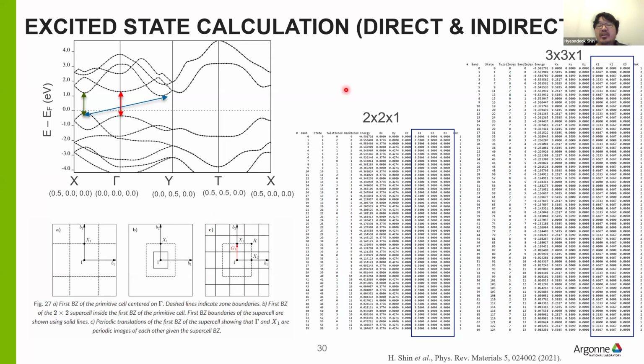So now we can make a strategy for how to shape the supercell to include the CBM and VBM for the indirect gap calculation for the monolayer system. We need to include the k points at 0.33, 0 and 0, 0.33 to estimate the indirect gap in this calculation.